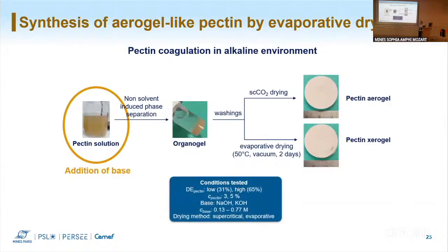It's not always the fastest, because contact with gas transfer with heat is not very fast. So have you tried to freeze your materials in a liquid bath at minus 30 degrees of alcohol? That's fastest. Yes, so the freeze drying was used only for the grafting of amines, and only to dry the materials without passing from high temperature technique, so from oven, in order to do characterization.